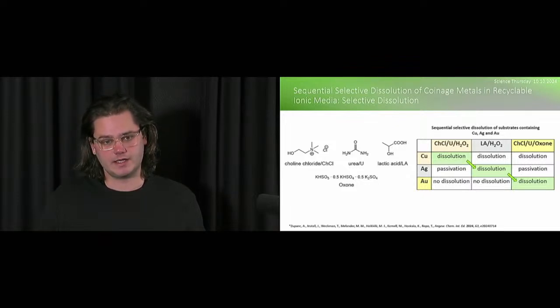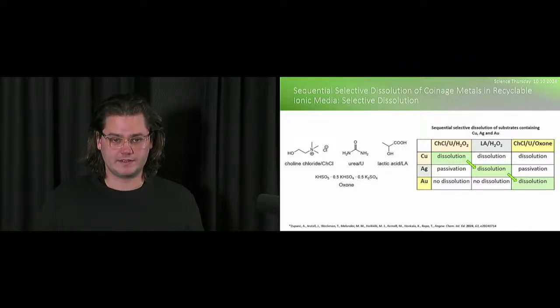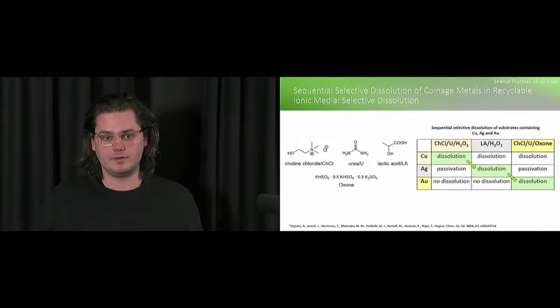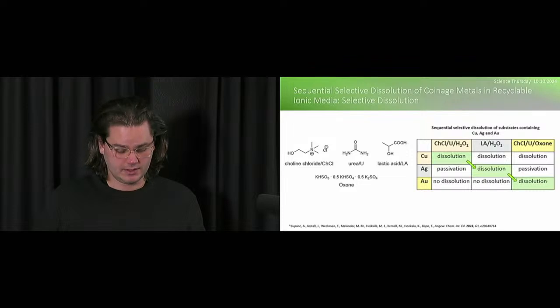So we were playing around with lactic acid based deep eutectic solvents, and we found out that lactic acid itself using hydrogen peroxide can dissolve silver, but also copper. But then again, we also had a system from before that could dissolve copper alone. Therefore, the sequential selectivity is that we have one system where we dissolve one metal. So if I go through this table, in choline chloride urea deep eutectic solvent, by using hydrogen peroxide, we can dissolve copper, whereas silver and gold are not soluble. Then we transfer this silver and gold with other parts of the waste to the next batch, and we dissolve selectively silver in lactic acid using hydrogen peroxide, where gold doesn't dissolve. And then for the last dissolution, we can dissolve gold using choline chloride urea oxone, and we can dissolve gold from other plastic and other waste materials.